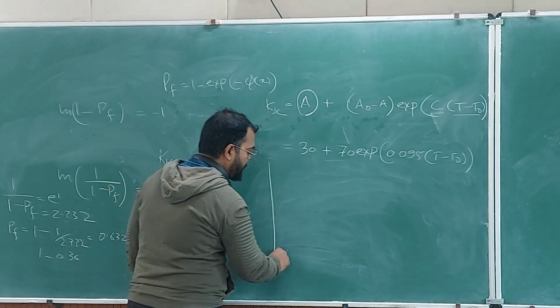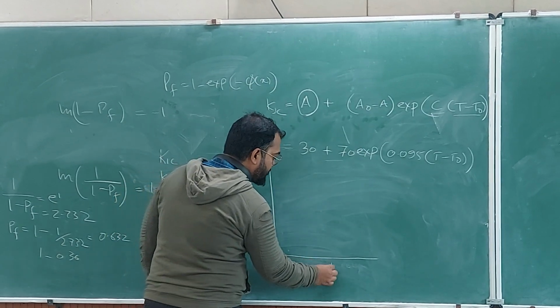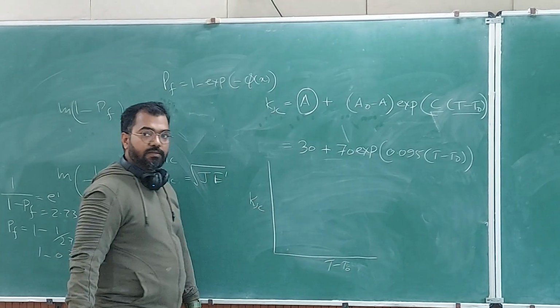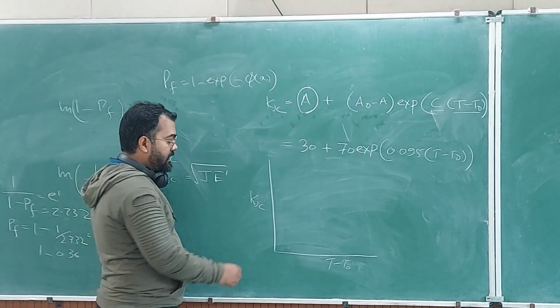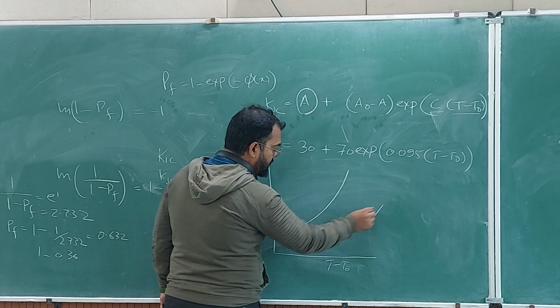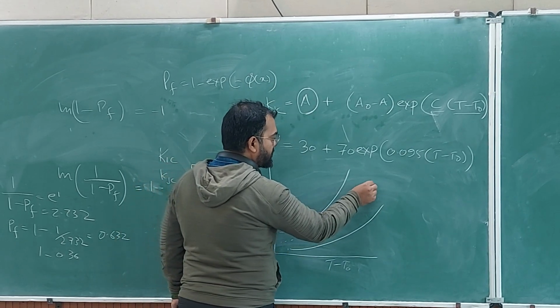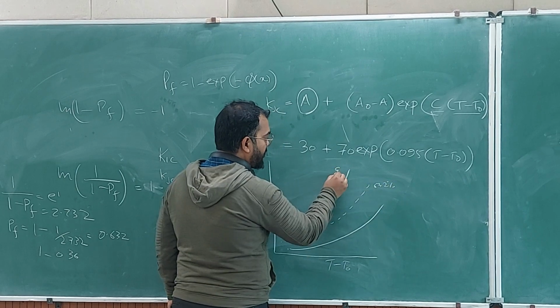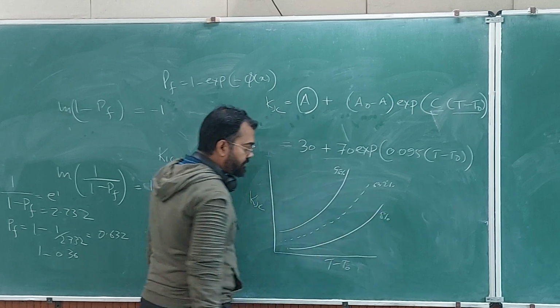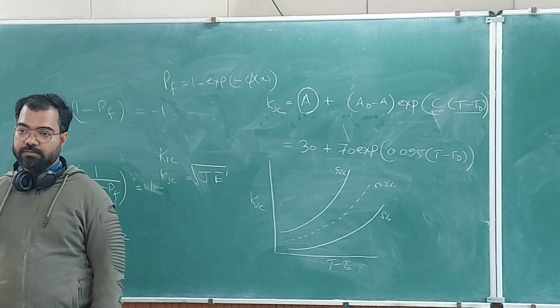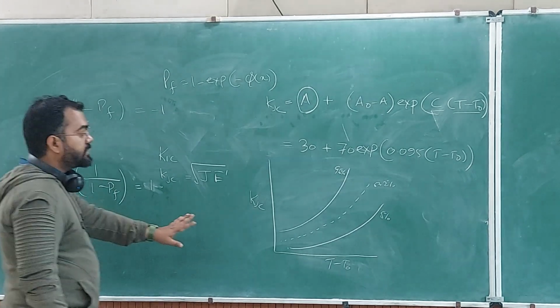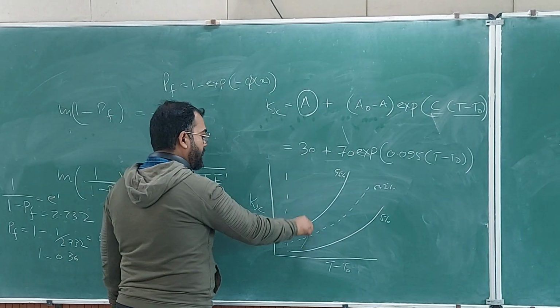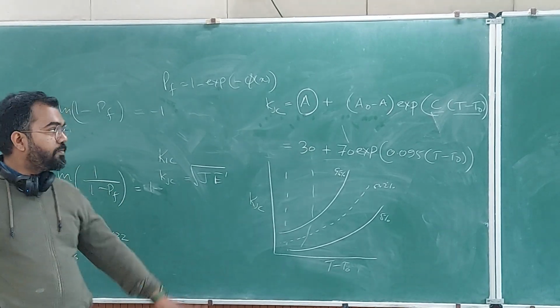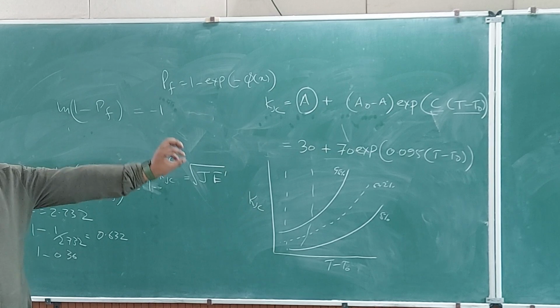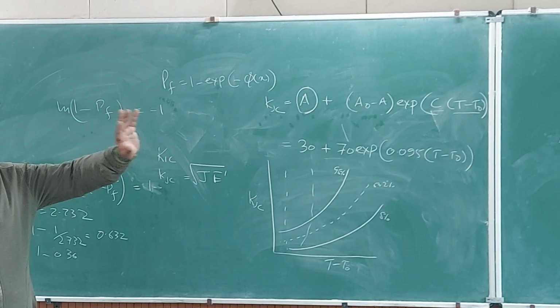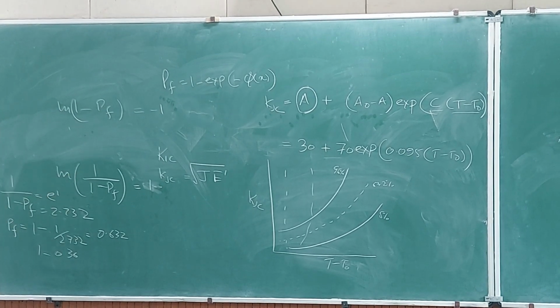Then when you plot KJC versus T minus T naught, when you do that for all the data which I showed, it follows a curve like this, and then you can plot the 63.2% probability, 95% and 5%. All the data falls in this range. If you don't have this kind of analysis and you just plot KJC versus T, you get a huge scatter. But when you do this, all the data falls on this curve, in this band. Nothing goes out. And it is generic in nature.